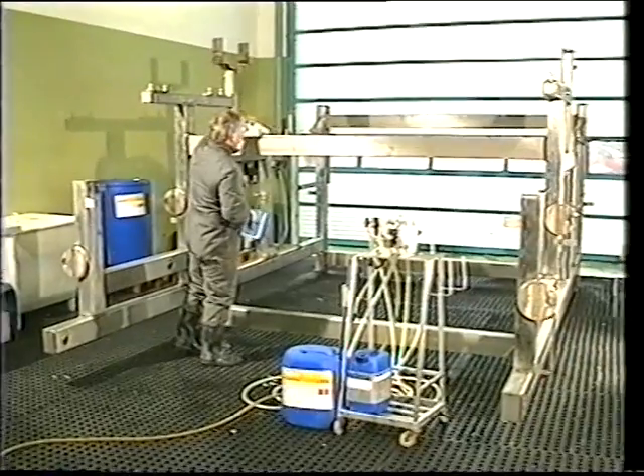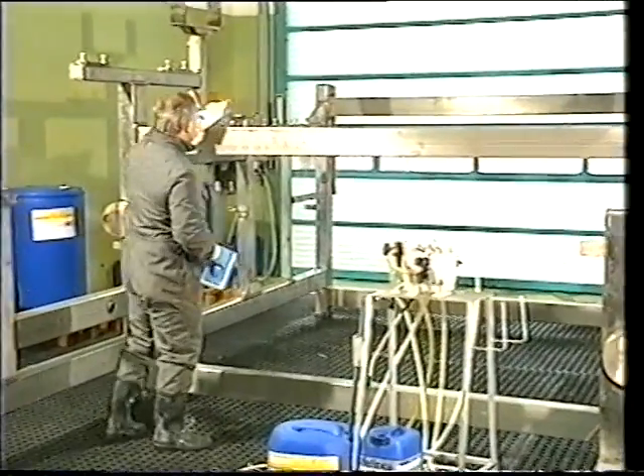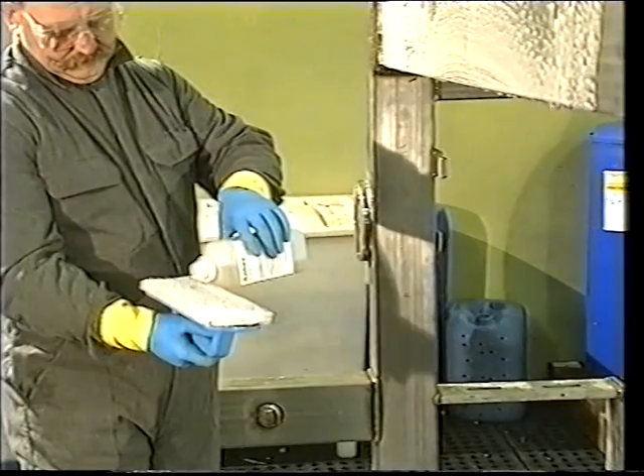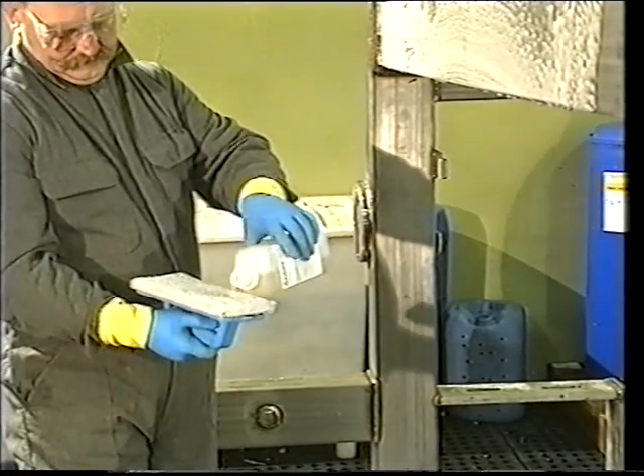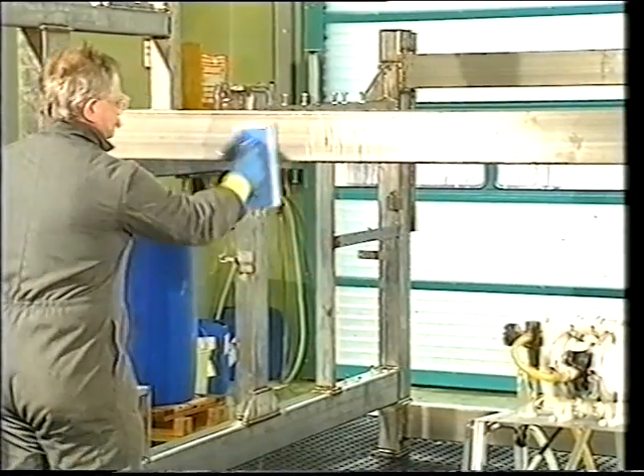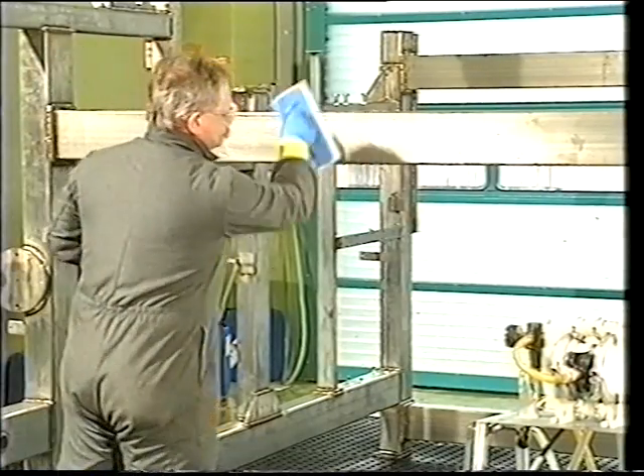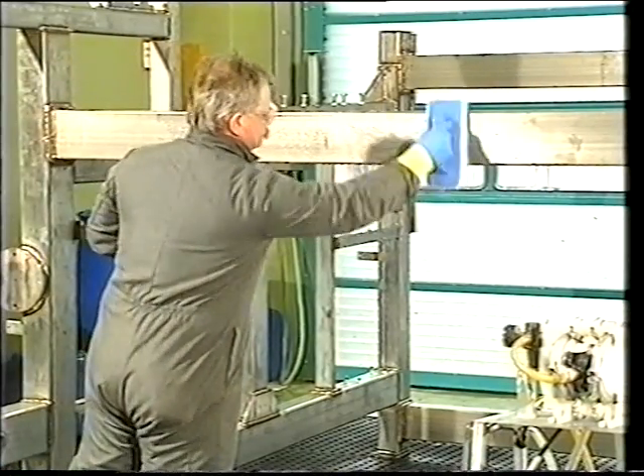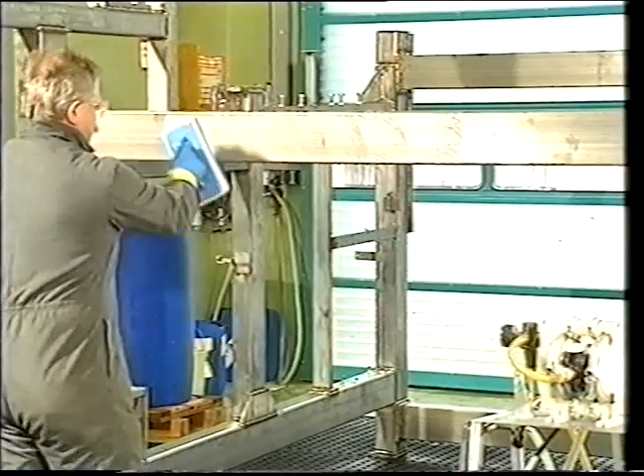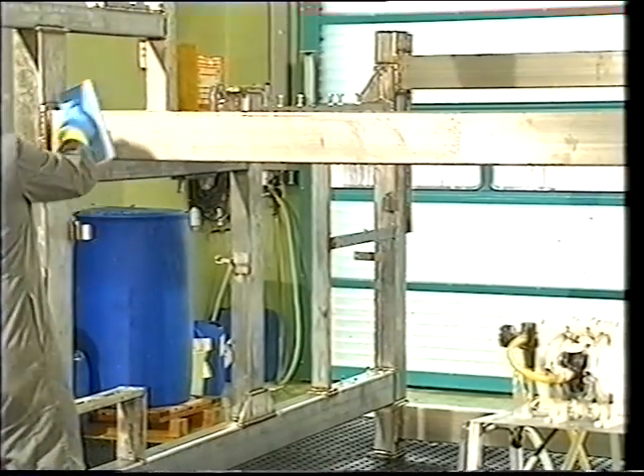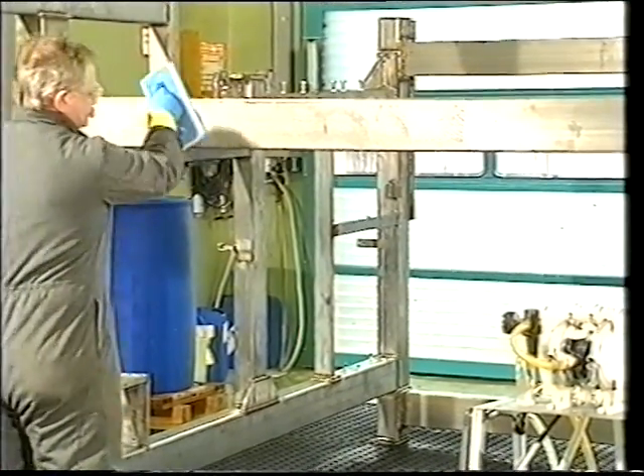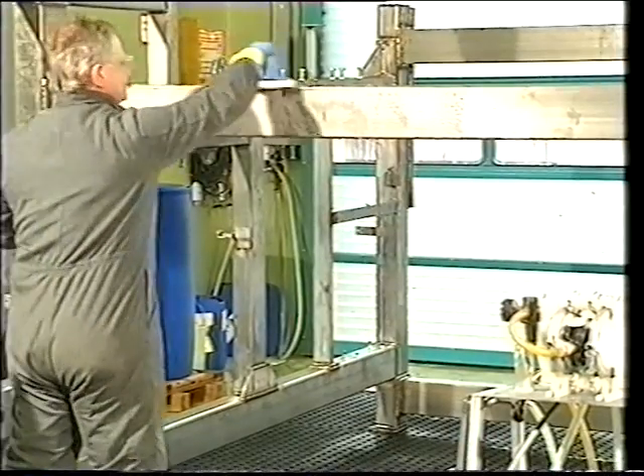If the shape or size of the parts precludes immersion, the pickling agent Metinox 73E is sprayed on. Once again, of course, the surface must be clean and grease-free. Since oil and grease are not attacked by acids, they must be removed before pickling with an oil-dissolving cleaner, such as Metinox 75E, which is either sprayed on or wiped on by hand as shown here.